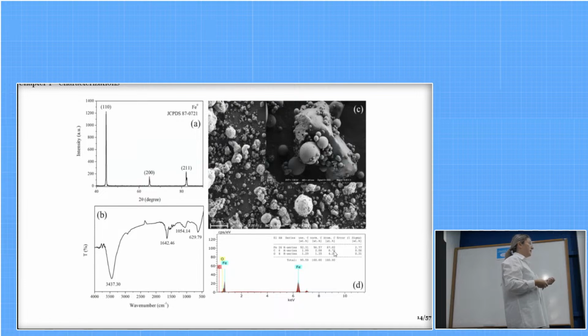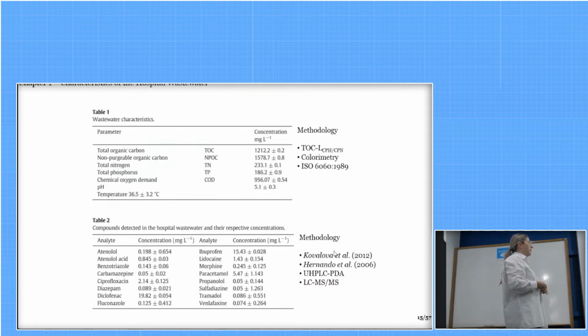We characterized the zero-valent iron in order to confirm it was a single phase of iron, as shown by the XRD analysis, and we also investigated the morphology of the material to confirm its characteristic spherical structure. Then the wastewater characteristics obtained show a high total organic carbon content, an even higher content for non-purgeable organic carbon, and a high chemical oxygen demand in this sample.